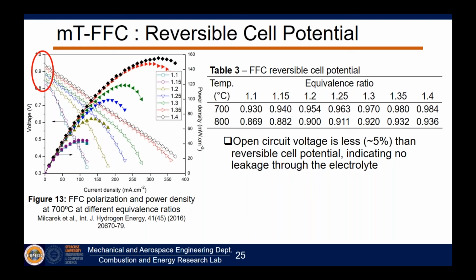Really exciting, right? But now let's talk about what happens when we start to draw current. As we start to draw current, so we're increasing the current density, notice what happens as we increase the equivalence ratio. Initially, we see essentially a curved line. This curved line, when it curves down like this in a fuel cell, means that the fuel cell's not getting enough fuel. There's not enough fuel available for it to go through the electrochemical conversion process it wants to. But as we increase the equivalence ratio, there's more syngas available, and it starts to become quite linear. You notice that?